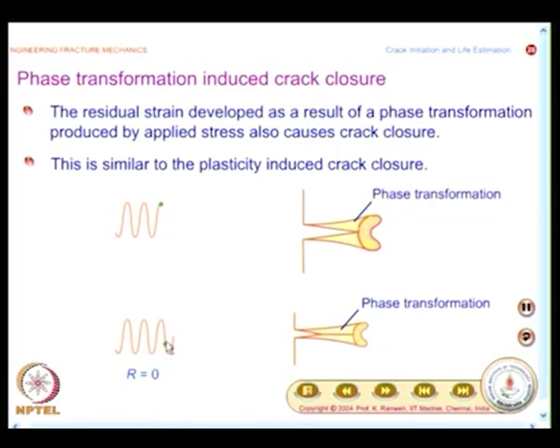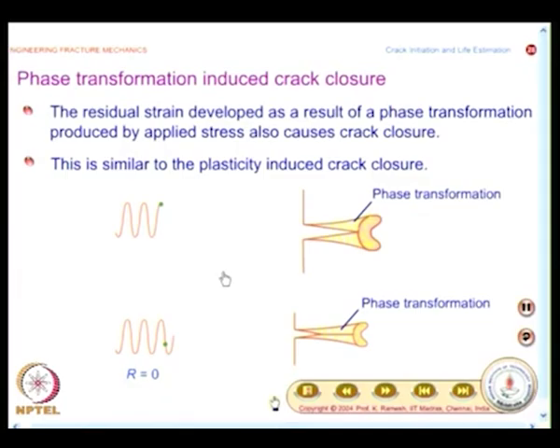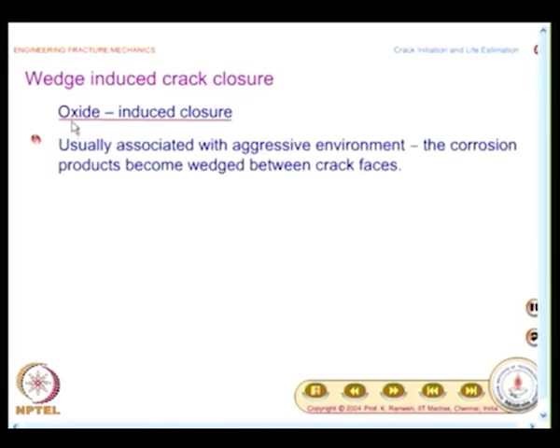And now you see when the load is reduced, before it reaches 0 the crack is closed, it is because of phase transformation. So, that is what is indicated here. Once people understood the concept of crack closure postulated by Elber, several other mechanisms have been identified. One is because of plasticity induced, here it is because of phase transformation, and the third case is wedge induced crack closure, it could be due to oxide,